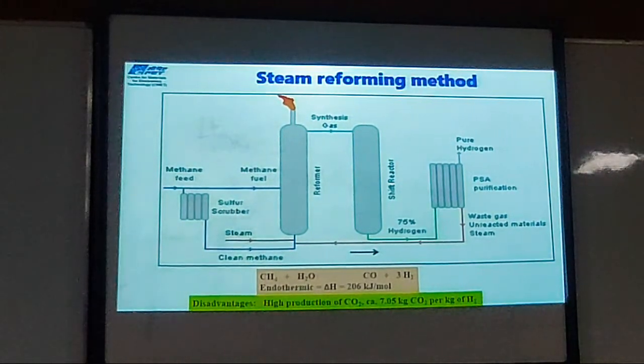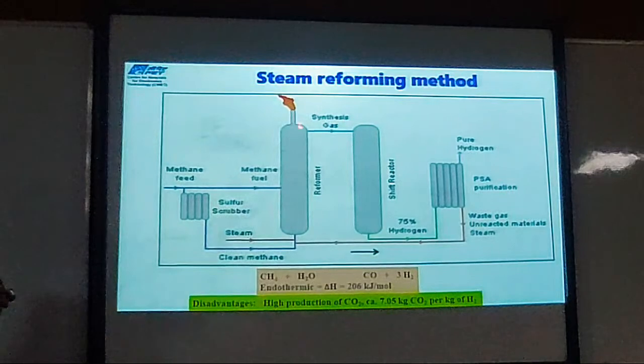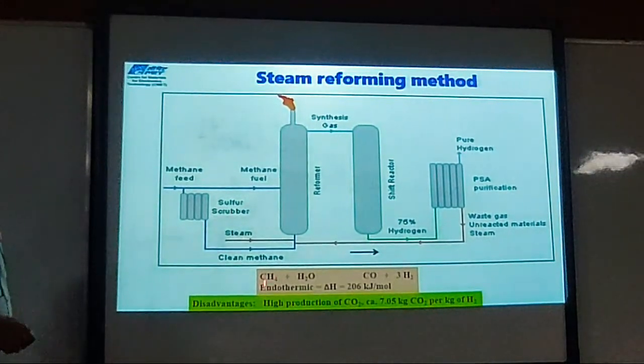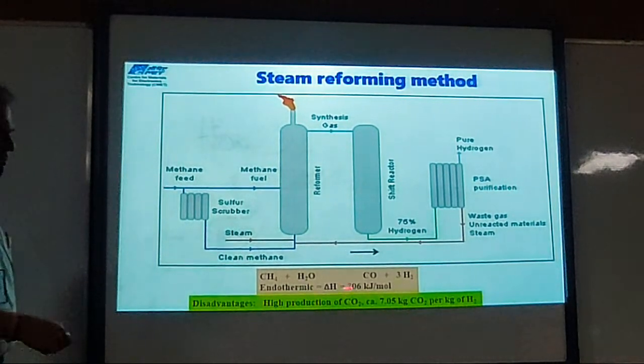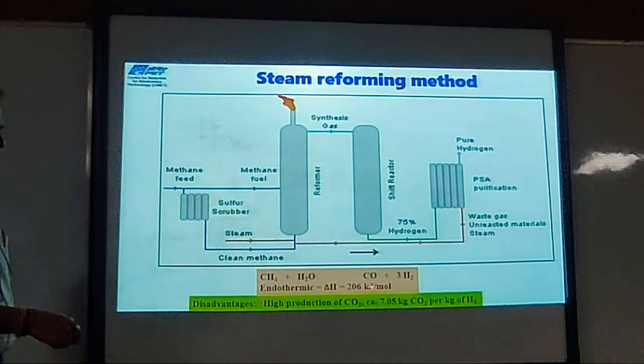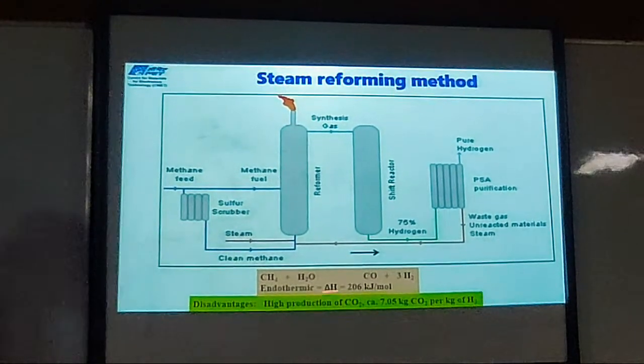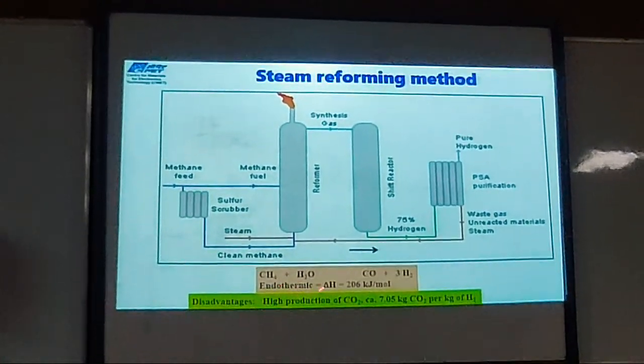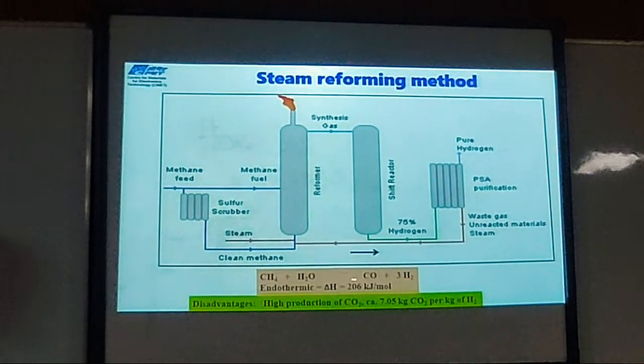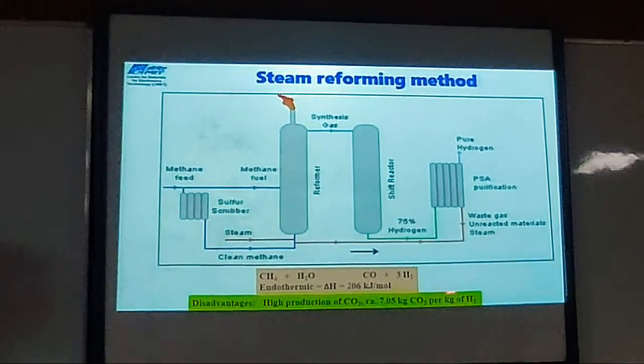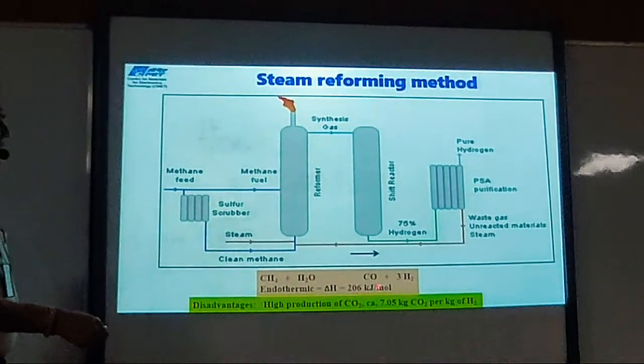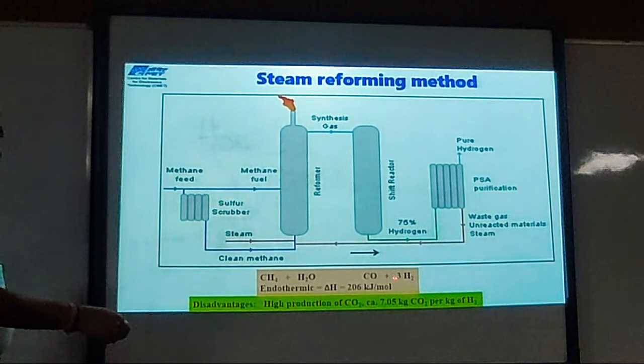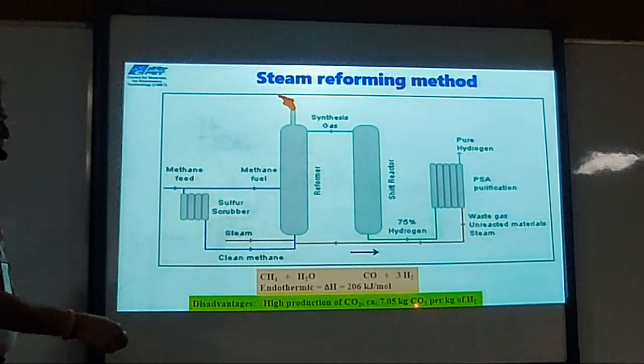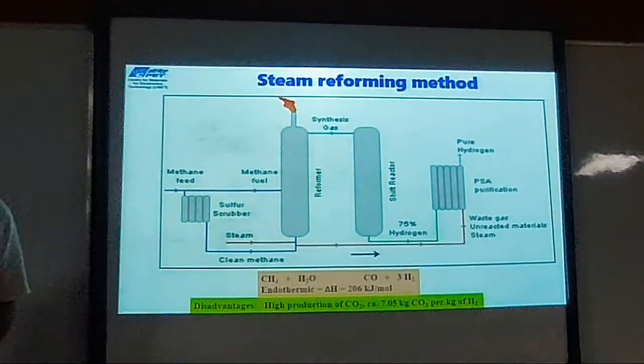This is the standard method of making hydrogen. This is the steam reforming method. In the steam reforming method, the methane gets oxidized, and it's a very highly endothermic reaction, 206 kilojoules per mole. It happens at some 800 degrees centigrade, and CO and hydrogen are produced. The problem here is how to get rid of CO. CO2 is also generated, CO plus CO2 and then hydrogen, so separation of CO2, CO and hydrogen is much more complicated in this process.